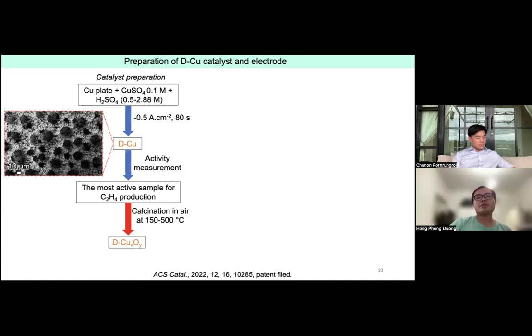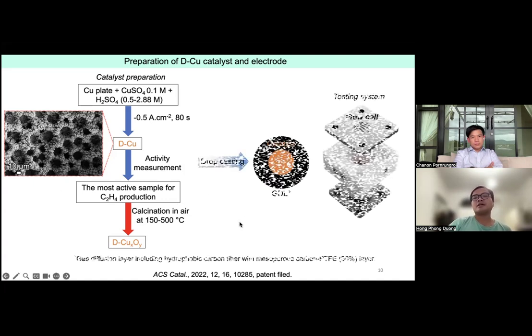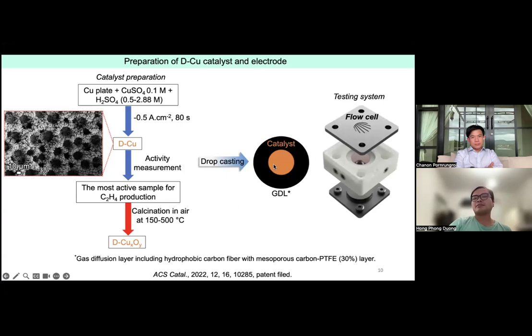Then we can perform calcination in air to vary the oxidation state of copper, because copper can have three different states: zero, one plus, or two plus, and each oxidation state can affect the selectivity of the reactions. After getting this powder, I perform the drop casting method onto the gas diffusion layer, which is called GDL here, the things I just showed you before, and then put it into the flow cell.